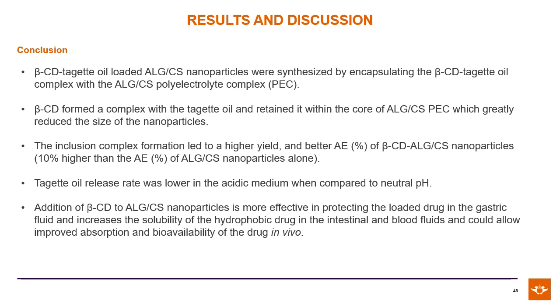In conclusion, we were able to successfully synthesize beta-cyclodextrin tagette oil loaded alginate and chitosan nanoparticles. We did so by encapsulating the beta-cyclodextrin tagette oil inclusion complex with alginate and chitosan into the alginate and chitosan polyelectrolyte complex. Beta-cyclodextrin formed a complex with the tagette oil and retained it within the core of the alginate and chitosan polyelectrolyte complex, which greatly reduced the size of the nanoparticles. The inclusion complex formation led to a higher yield and better association efficiency of beta-cyclodextrin, alginate, and chitosan nanoparticles.